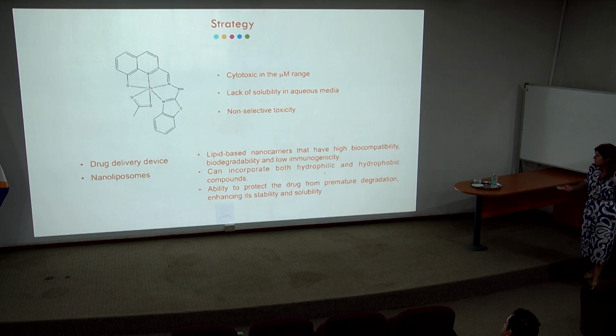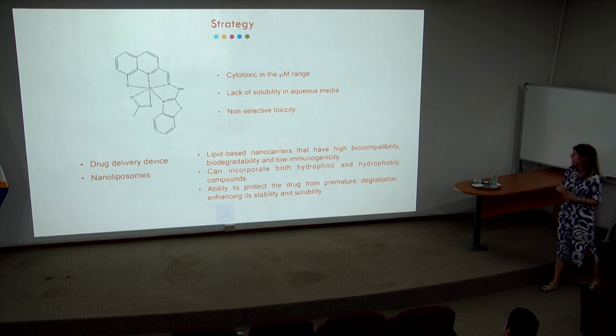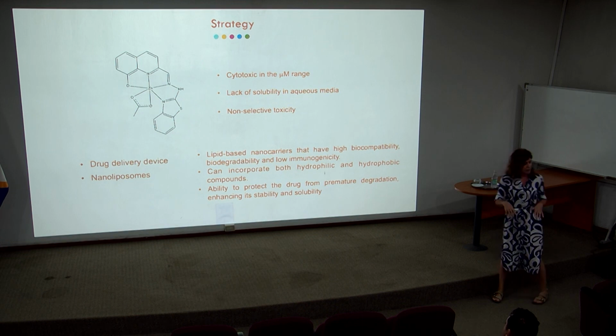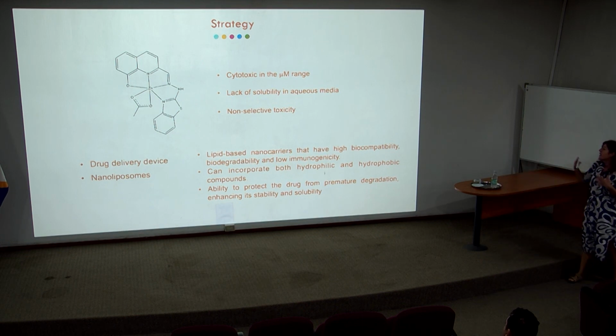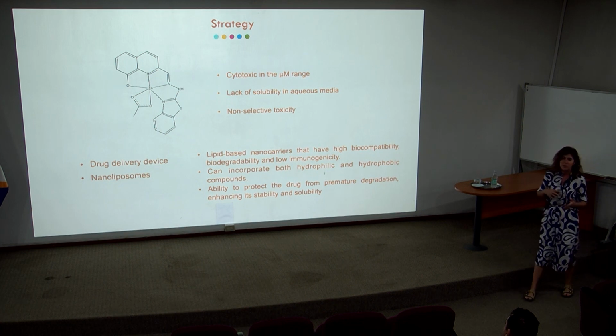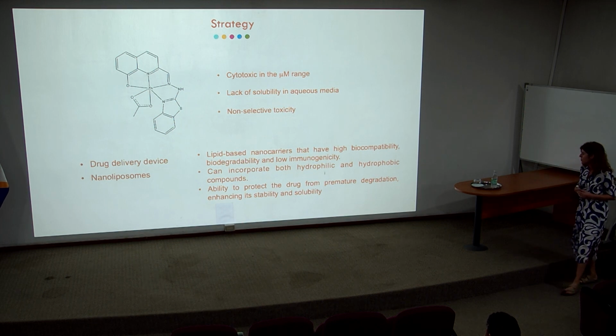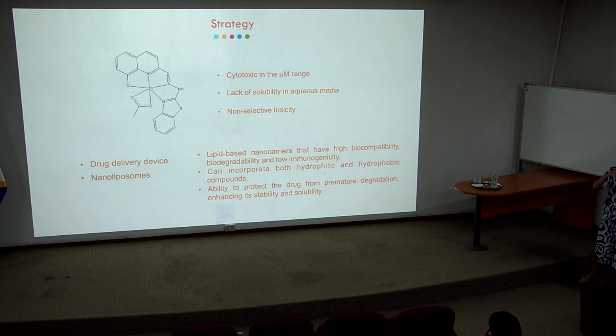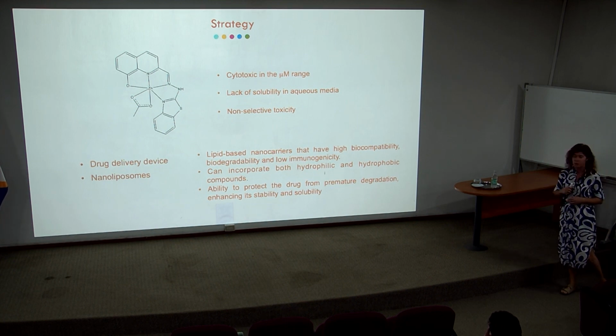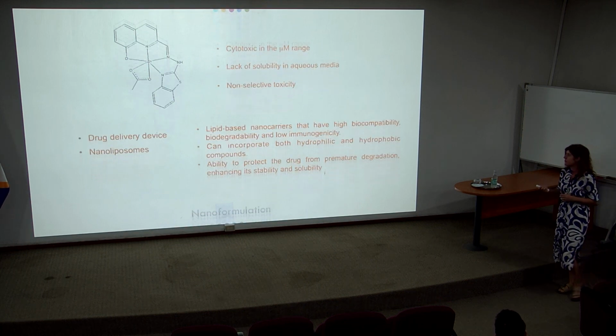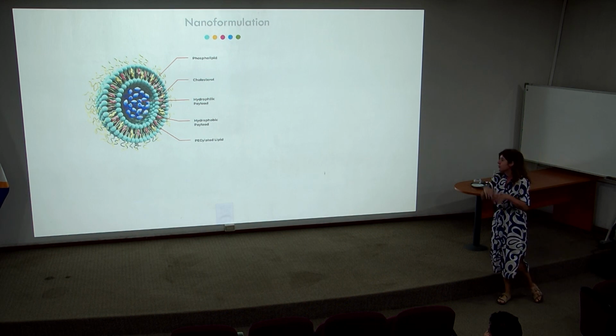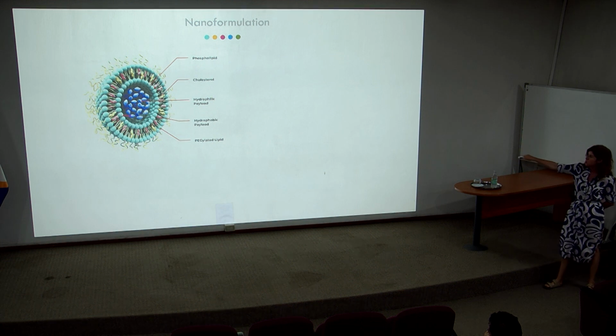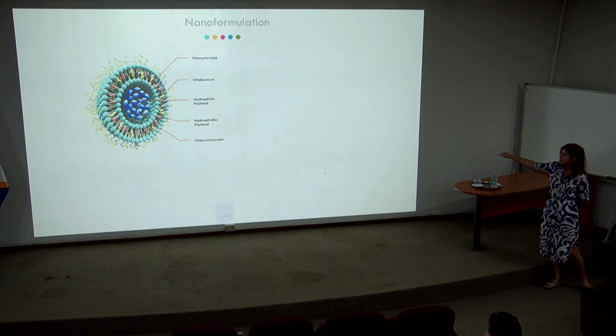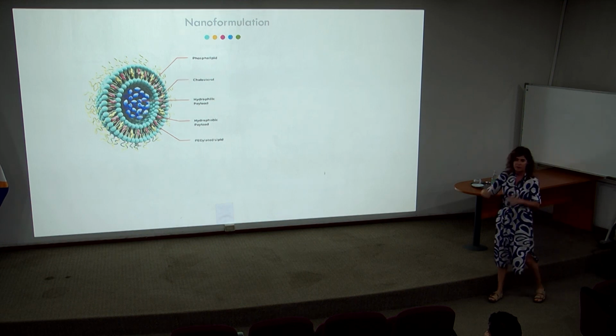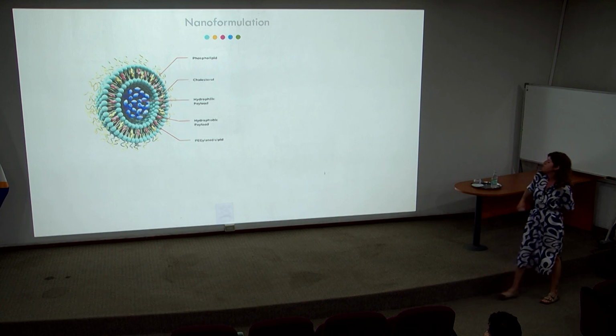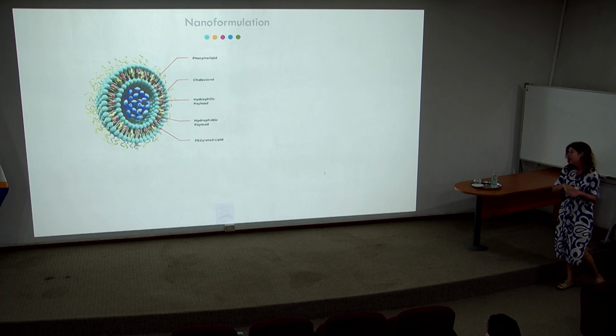What are nanoliposomes? They are lipid-based nanocarriers, and it is considered that they have high biocompatibility, biodegradability, and low immunogenicity. And the good thing is that we can incorporate hydrophilic or hydrophobic molecules, and typically when we incorporate drugs in these lipid systems, we protect the drug from degradation, enhancing its solubility and stability. So this is a drawing of a liposome. Hydrophilic drugs will be incorporated here. Hydrophobic drugs, like our complex, will probably be incorporated in the lipid bilayer. And typically we include PEG, a polymer, which increases the blood circulating time.